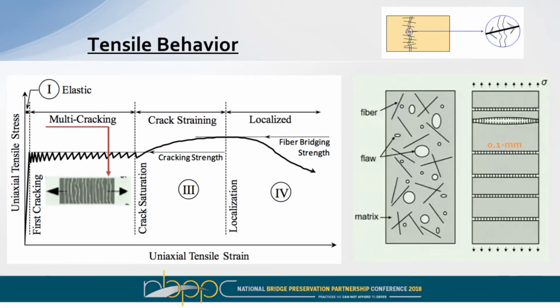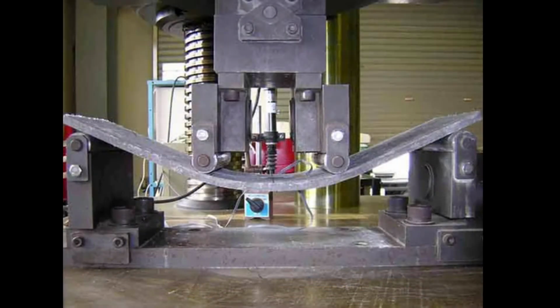So they virtually remain impregnable to chlorides and water and acids and aggressors and all these fun things that deteriorate our structures. But they also add a neat feature: they give concrete flexibility. So you can cast a very thin panel of this material and you can literally bend it like you would a plywood piece. So obviously you're not going to do this to your bridge deck, but it shows you that in order for this element to bend, hundreds of cracks have to be forming to give it that displacement. And you can't really see one singular crack anywhere on this element. So all these cracks are very fine and evenly distributed across the stressed area there.